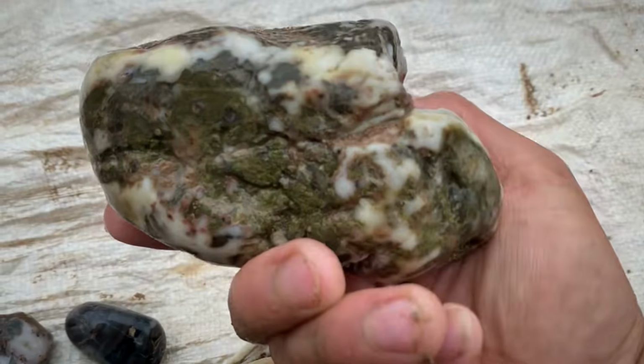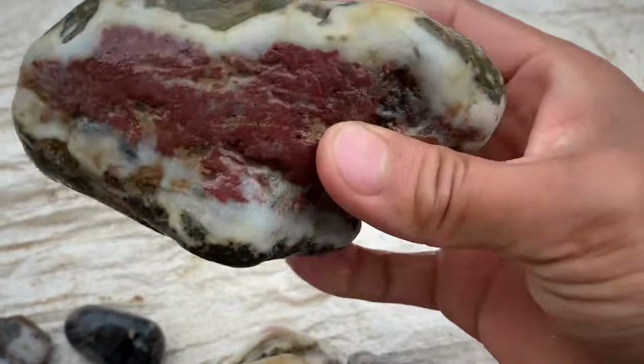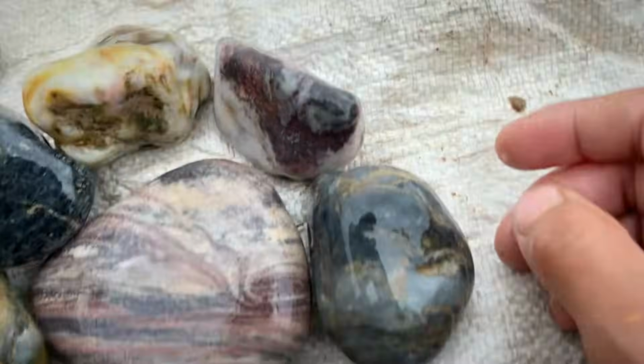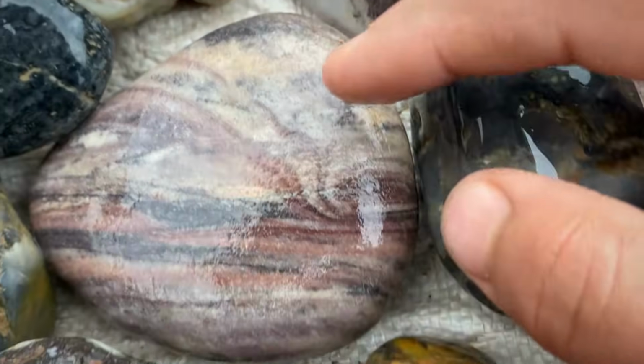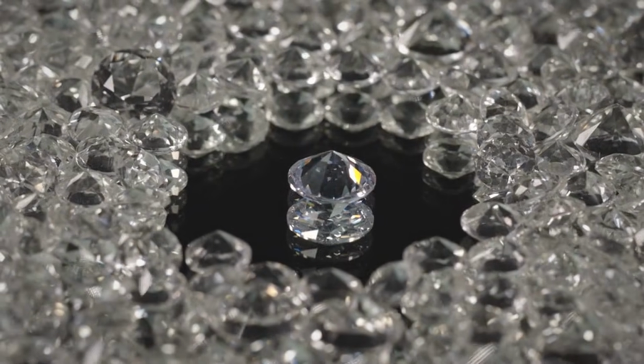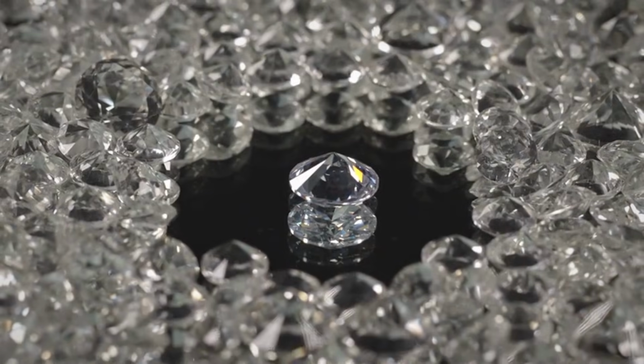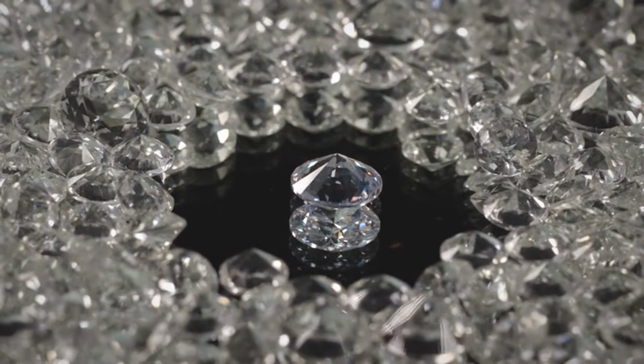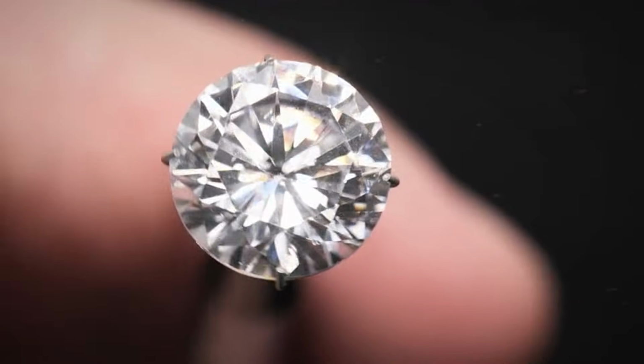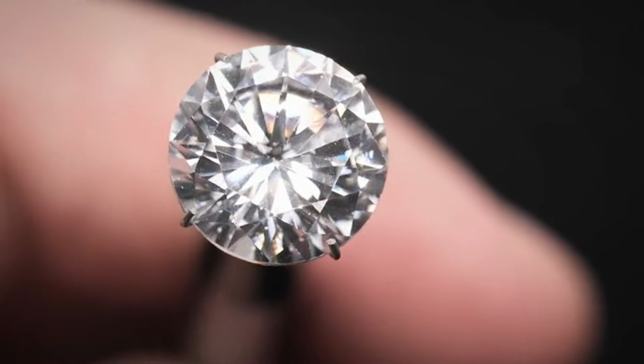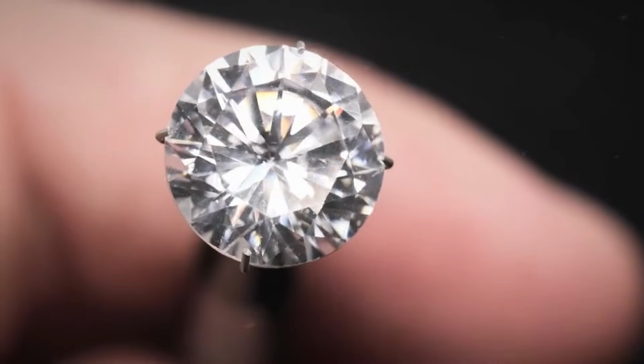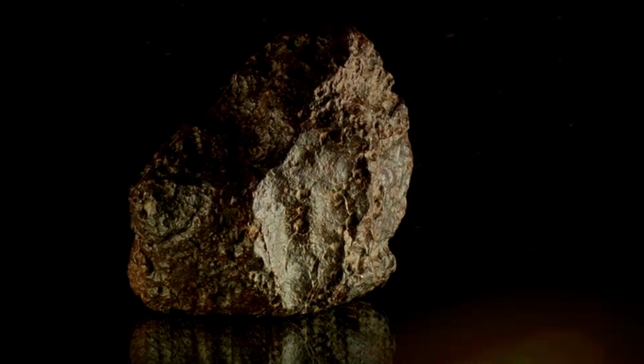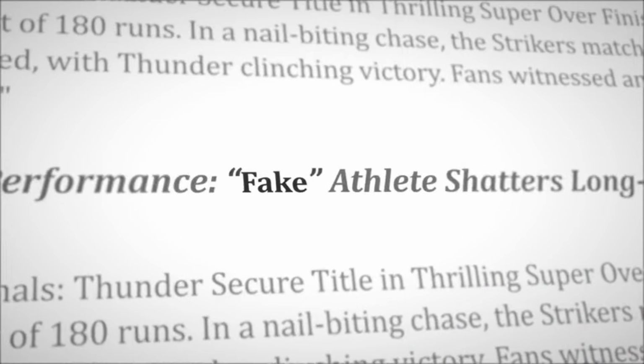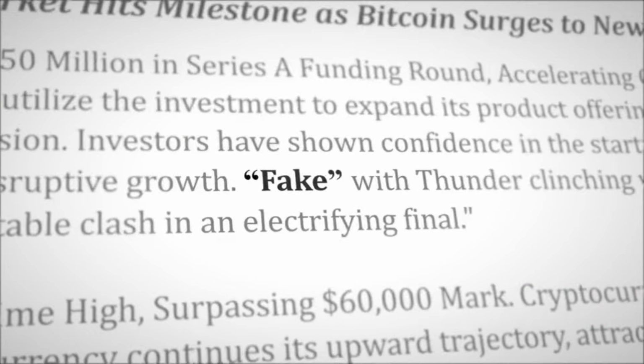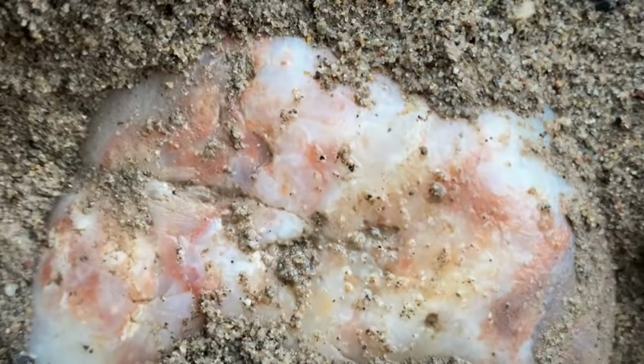Composite stones may resemble diamond in color and shape, but their internal makeup exposes them when placed on the scale. Even moissanite, the best mimic in most other tests, rarely hits 3.52. It generally measures between 3.20 and 3.25, enough to cast doubt when everything else seems too perfect. And if you're testing a stone that fails gravity outright, say, measuring 4.0 or above, it can be eliminated from consideration as a natural diamond in seconds. At this point, most fakes have been ruled out or strongly flagged.